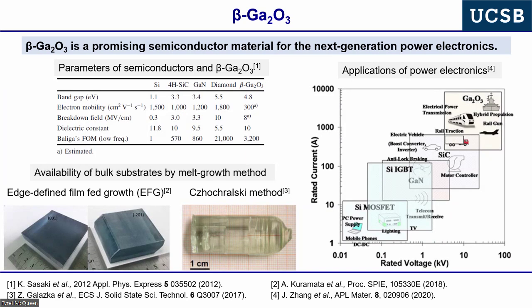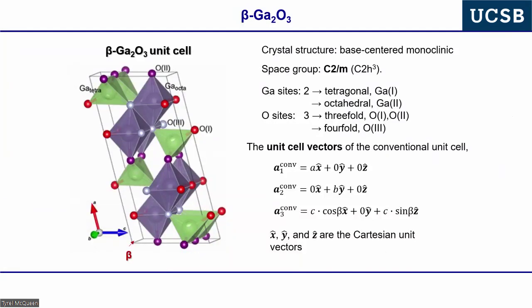The preferred method would be Czochralski growth or vertical Bridgman growth for these crystals, because in principle, those techniques will have less loss of the crucible material. One of the worries in our field is that the iridium loss, these are grown from iridium melts in iridium crucibles, is actually a cost limiting factor. So we're still considering what would be better growth techniques that are lower cost, okay? And then this just gives you a survey. If we have these kind of breakdown strengths with these kind of crystals, and many other things that I'll talk about today, there are kinds of technologies that we would move into, either direct high voltage technologies, but where we're mostly interested is looking at grid scale technologies, going from low voltages to very high voltages for the devices.